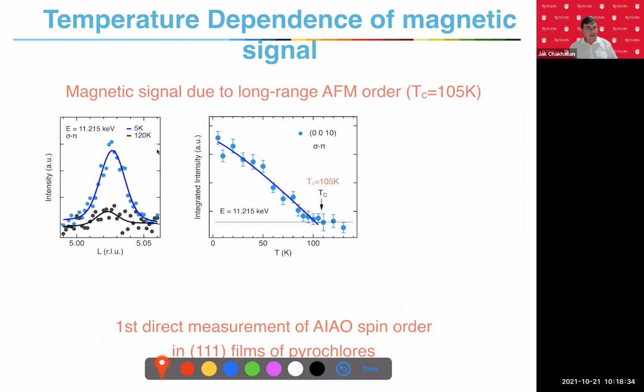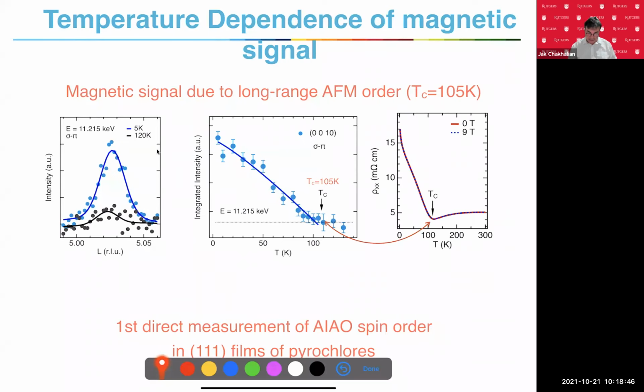So now it's not the imagination. Now you can really be very confident that these materials have the transition into this unique all-in, all-out antiferromagnetic state at this temperature. And it really coincides with the transport you measure in your resistivity. So it's very beautifully coherent, with the same number.